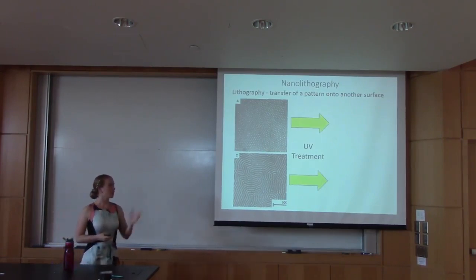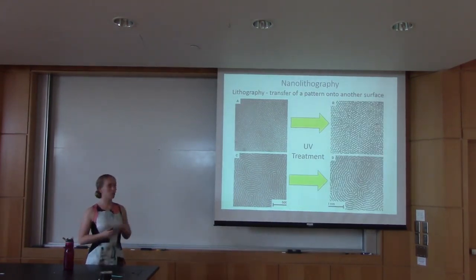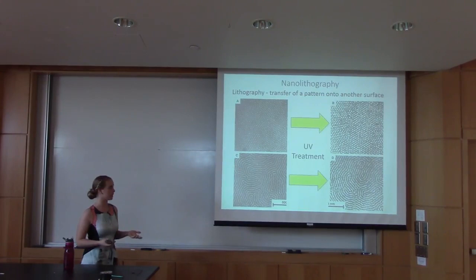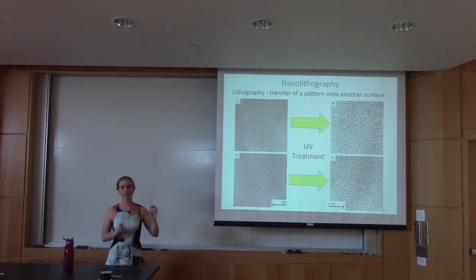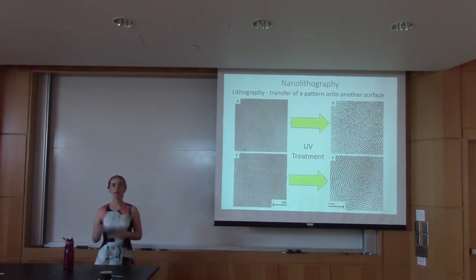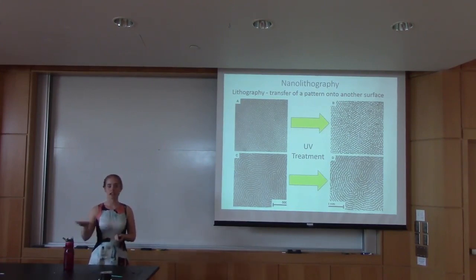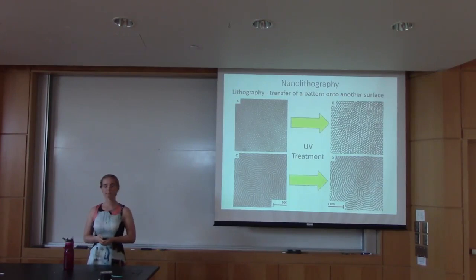And with that, we apply our UV treatment that preferentially gets rid of one part of this pattern, so one of the polymers, and in this instance it's the darker polymer, and we're left with these white voids. So with that, we now have a pattern we can use. Instead of just being a flat surface, we have these grooves, and we can pattern our circuits using this.